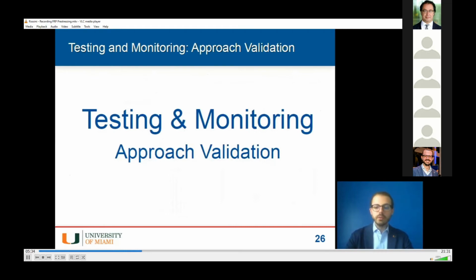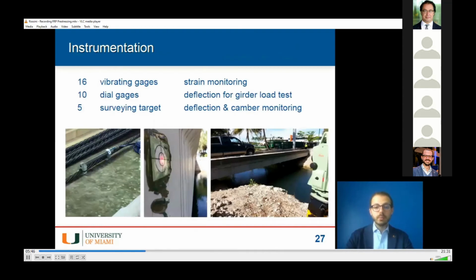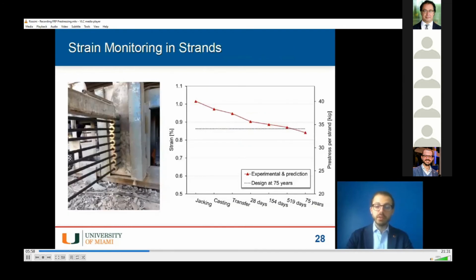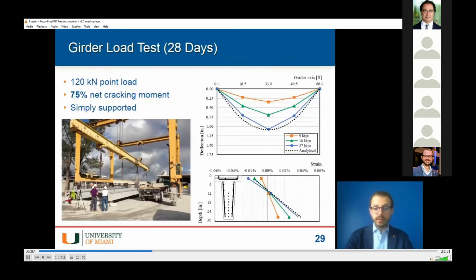Let's move to a more exciting part of this presentation. In order to make sure that our design approach was reasonable, made sense and was working, we had to test and monitor our structure. In order to do that, we placed quite a number of instruments in our bridge, including vibrating wire gauges, dial gauges, and survey targets for monitoring during in-service conditions, and we performed a series of load tests. First of all, here we see the strain monitoring in our girders during pre-tensioning and during the first years of service, and we see quite a good agreement with expectation.